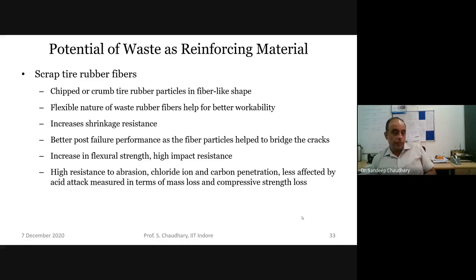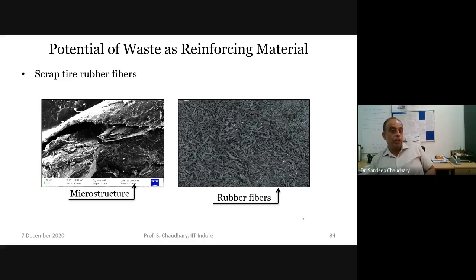So, like we can use scrap tire rubber fibers as a reinforcing material. Again, of course, here we are getting an increase in flexural strength, but use of fiber does not necessarily mean that we'll get an increase in the flexural strength. What is important here is we get a high impact resistance, and anyway high resistance to abrasion, chloride ion and carbon penetration, etc. So this is the microstructure of scrap tire rubber fiber.